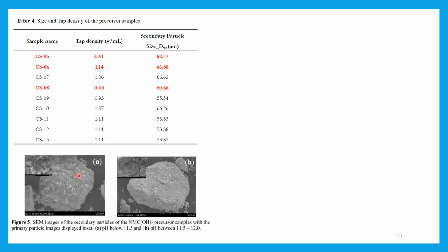And then we did the electron microscopic analysis using an SEM. But basically, we found that for all these samples, when it precipitates out of solution, it initially precipitates as these small nanoparticles, nanoplates, which then agglomerate to form these secondary particles. And then we found the orientation of these primary particles is also dependent on pH. So if it's below 11.5, the primary particles will mostly be vertically arranged, while those synthesized at a pH above 11.5 will be more horizontally arranged.